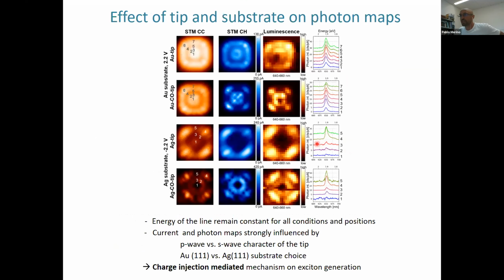And as I told you, we studied molecules on salt on gold and molecules on salt on silver. We see that we are using different polarities. In this case, for gold, we are injecting electrons into the molecule from the tip. In this case, we are injecting holes from the tip to the molecule. And what is important is that despite the energy of the line, the energy of the excitons, the electron-hole pairs, always being constant, the intensity can vary quite a lot depending on the choice of the tip and the substrate. We see here in these 4 photon maps that we have very different photon maps on the same molecule, on the same system. This is an indication of a charge injection mediated mechanism for exciton generation. I don't want to go into details because this is still an open issue in the community, but if you are interested, we can discuss it later.